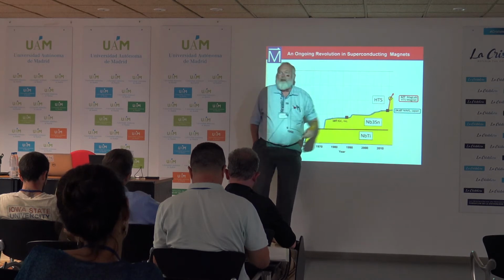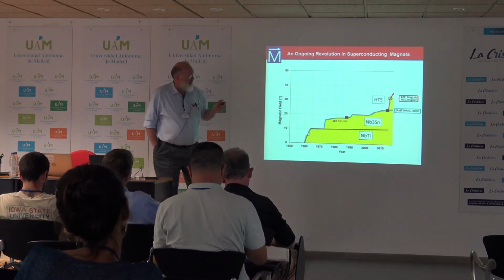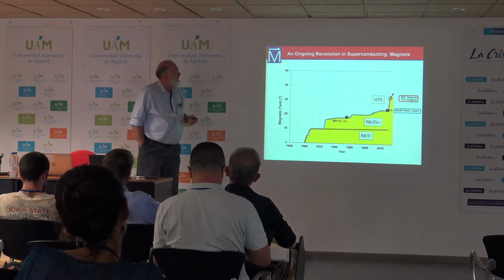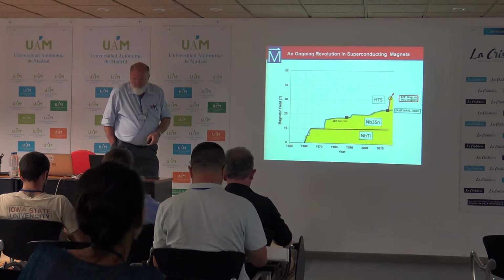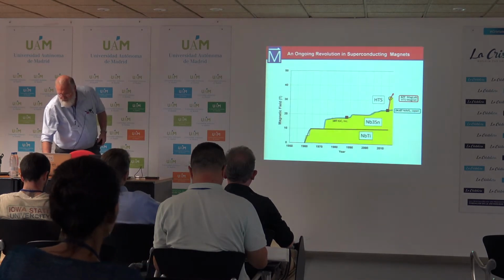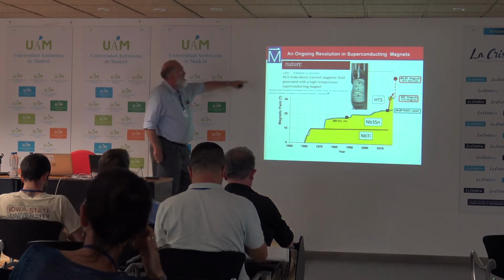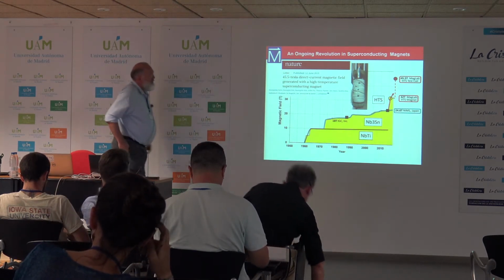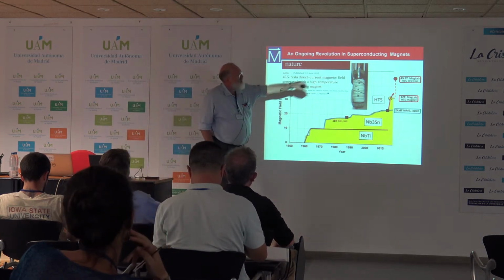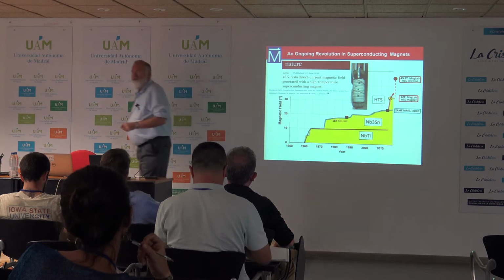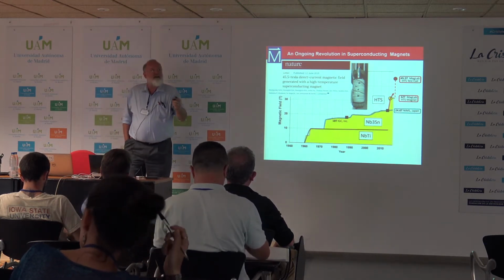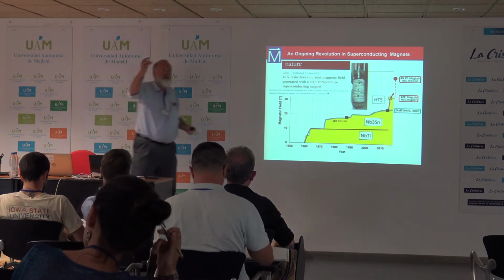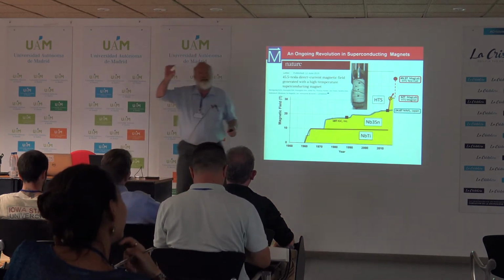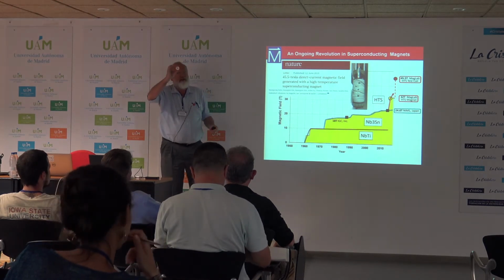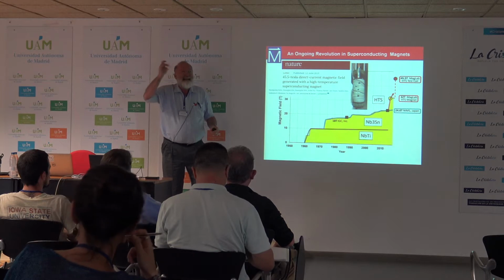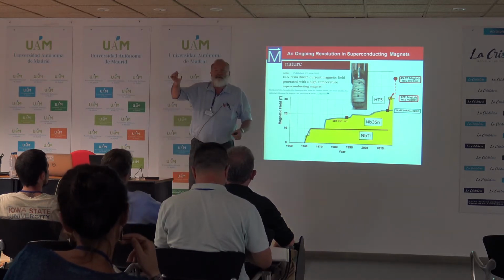And now HTS is starting with its advance. And we've got a 32 Tesla, all superconducting magnet at the Magnet Lab. Well, it seems to have frozen up. There we go. And just this year, just a few months ago in Nature, there was an article where we achieved a test coil, proof of principle, of 45.5 Tesla with a small coil inside one of our resistive magnets. So 31 Tesla was from a resistive magnet, but the insert coil, which was this size, they only give me the nylon version as the manager, this size of coil generated 14.5 Tesla in the bore, inside a 31 Tesla magnetic field. So the world will change.